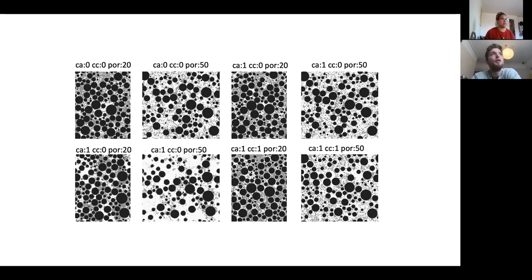It depends how large your image is and how statistically significant that artifact is. As in, if you have a single artifact, then you may see that. However common your artifacts are, that is how common they will be in your output data set. The whole idea is that we capture a distribution of features, and if an artifact is a feature, it will be captured. So the idea that we need a realistic training image is definitely true, but that is kind of the case no matter what simulation you're trying to do on microstructure. We always have to deal with artifacts.